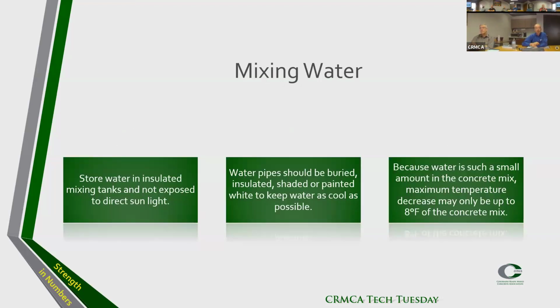Mixing water should be stored in insulated mixing tanks, not exposed to direct sunlight. If they are, at least paint them white. Same for the water pipes: bury the water pipes, insulate them, shade them, or paint them white to keep, again, the water as cool as possible. And again, water has a very high heat capacity, but because it's a pretty small amount, generally you can only decrease the temperature by about 8 F in the concrete mix.